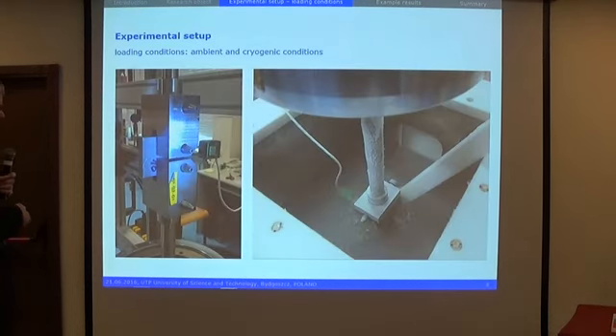The tests were, of course, realized in both conditions. For ambient, it means about 20 degrees Celsius, and in cryogenic condition, it means about minus 197 degrees Celsius. Of course, during the test, we have measured the COD in both conditions. Additionally, in ambient condition, we have the possibility to measure the crack length with the use of special equipment.